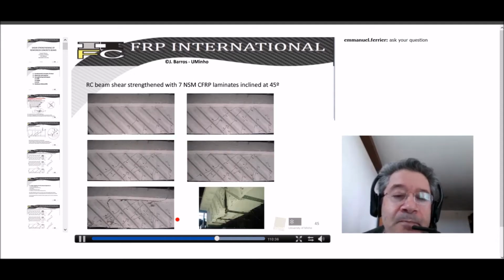However, when we use a relatively high content of laminates, we observed this type of failure mode that is formed by the detachment of the concrete cover. It is like a wall that is in fact the concrete cover layer where the laminates are installed, and this happens mainly when we have a relatively high content of CFRP laminates.